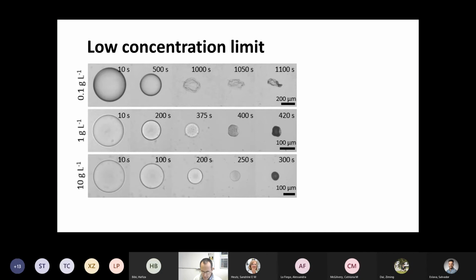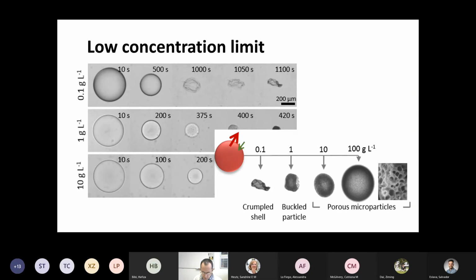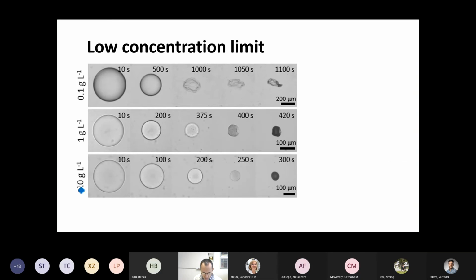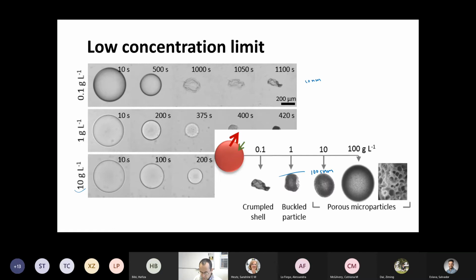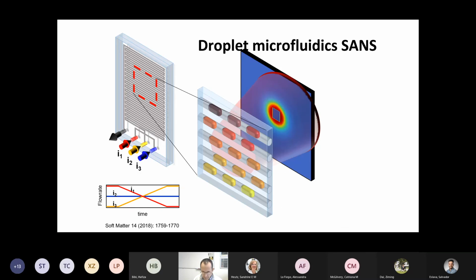Of course, you can take this to the lowest concentration limits and find out what you can do to wrap things around with this technique. And so you can eventually create, at such low concentrations, shells that are between hundreds of nanometers to just a few tens of nanometers over here. These are really tight skins. The films are continuous. It's as if you are effectively spin coating on a spherical geometry. And then, of course, you can contain materials, both interacting and non-interacting, within these.